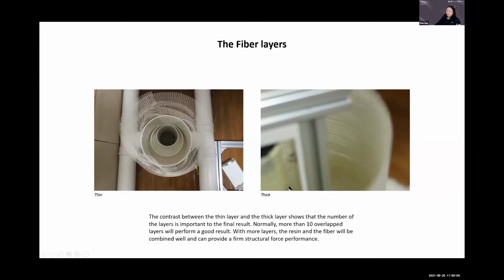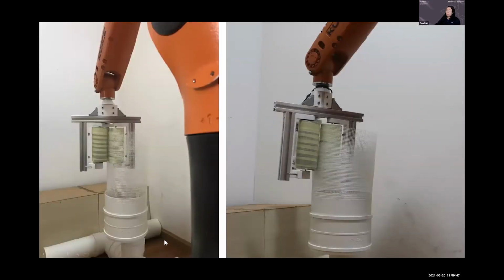In this kind of fabrication with fiber reinforced polymers, the support and the system rely on the cross-lamination between the layers. So it is essential to ensure that the fabric is cured correctly so that it is self-sustainable, and that the right amount of pressure and speed is coordinated so that each layer is laminated correctly, because the cross-lamination and the tightness of the system directly relate to the later structural performance in terms of reinforcement. Also, there is a trade-off between the layers and the fabrication speed. Of course, the more layers, the more solid the system is, but it multiplies the fabrication time.